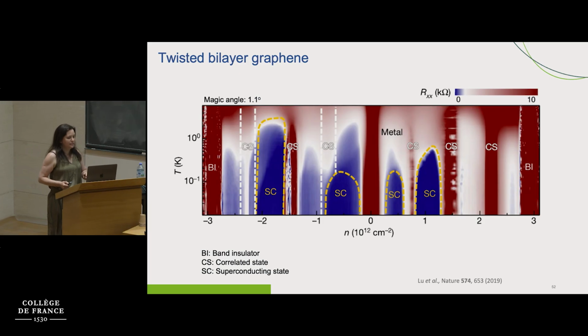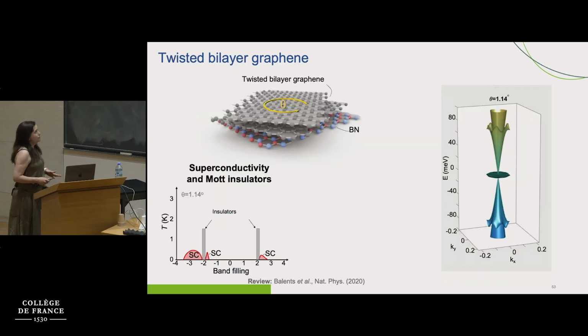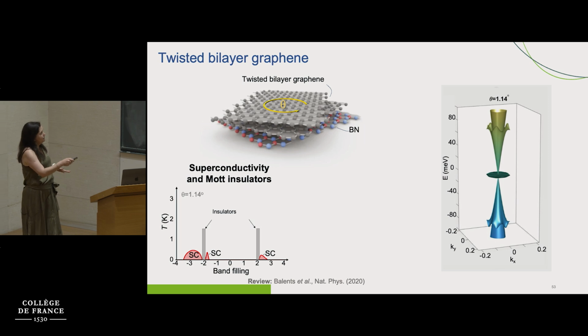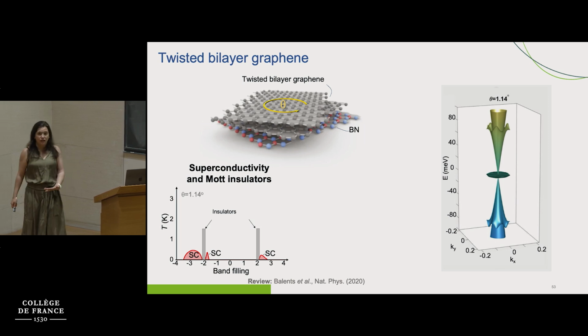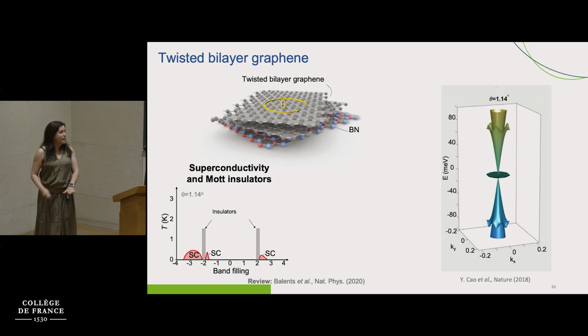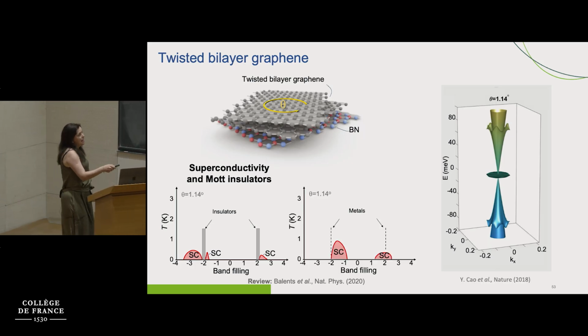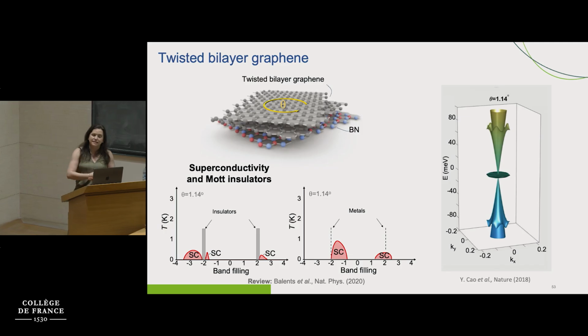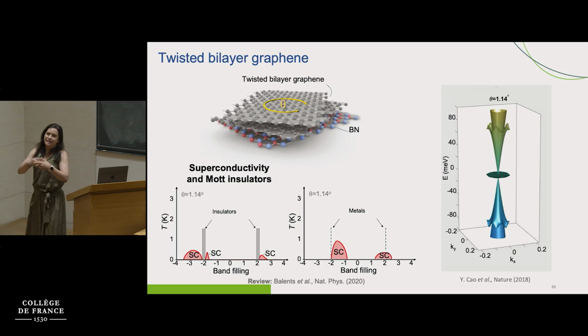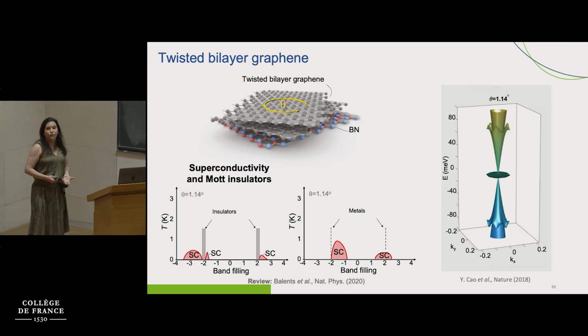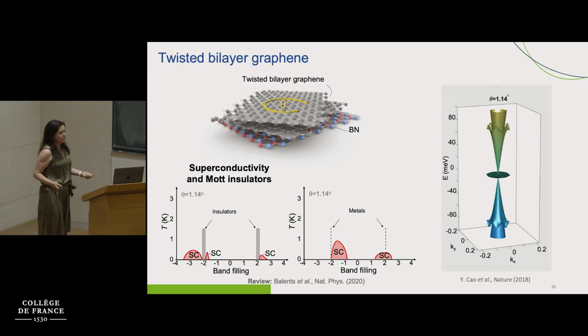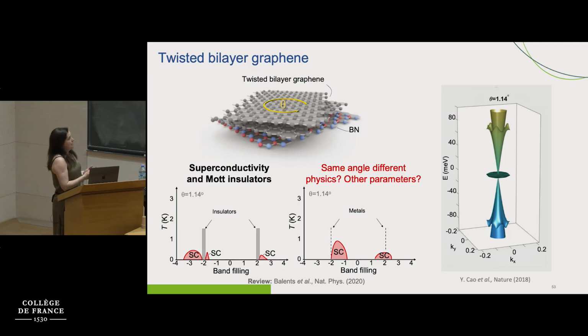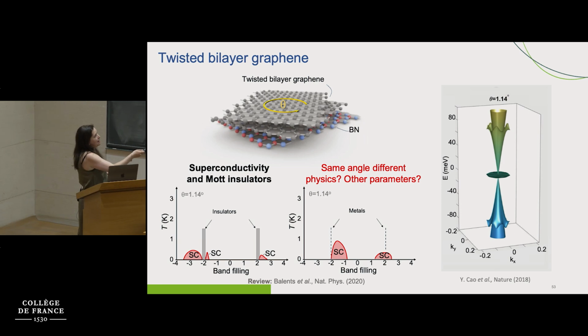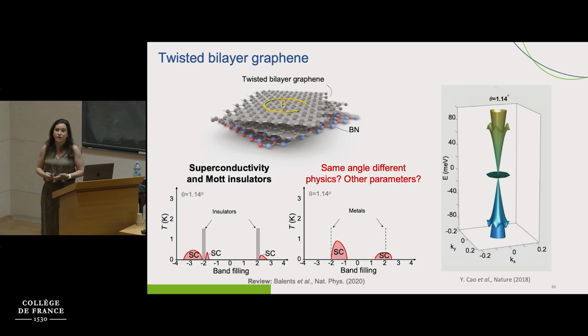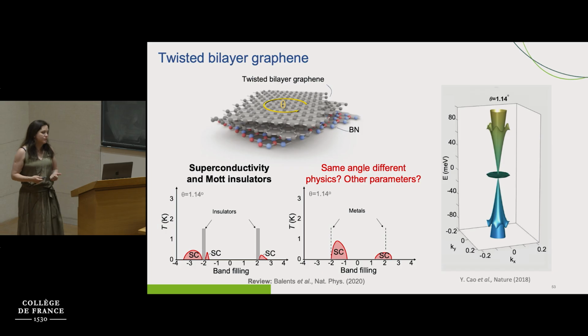However, there is a problem with twisted bilayer graphene. The main problem is that you can have a beautiful zoology of states to study, but if you try to replicate exactly the same angle with exactly the same characteristics, you might find something that is different. And this is related mostly to angle disorder, strain, the commensurate state that I told you before is also playing a very important role, the relaxation of the atoms. But this is also a very active research topic at the moment: how can we have the same angle but different physics? What are the other parameters that are playing an important role here?